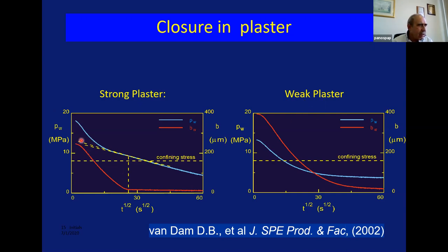In the case of the strong rock, you will see that when the pressure in the fracture drops near the confining stress on the block, the fracture had closed. You can see here in the red line that the fracture had closed. We are quite close. Now, if we go to the weak rock or weak plaster, you can see that when